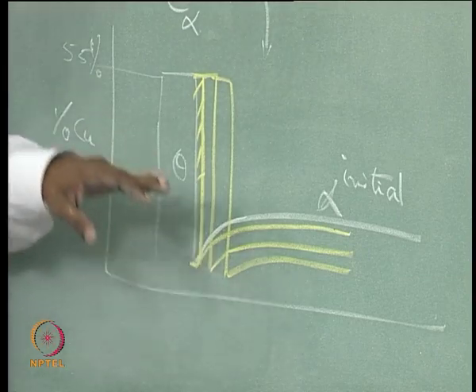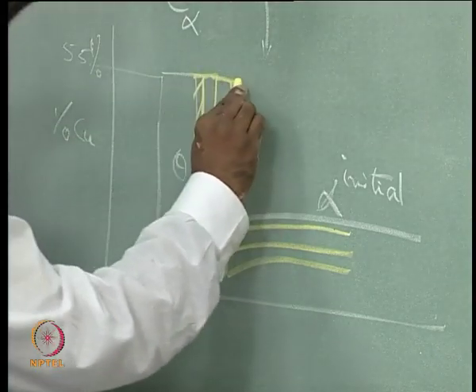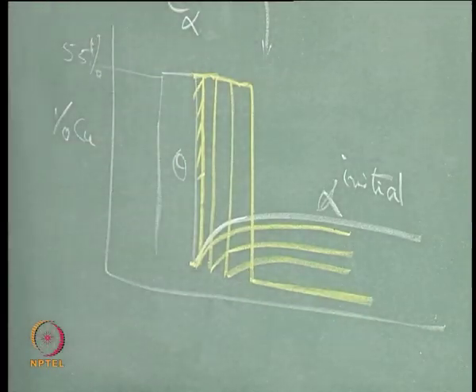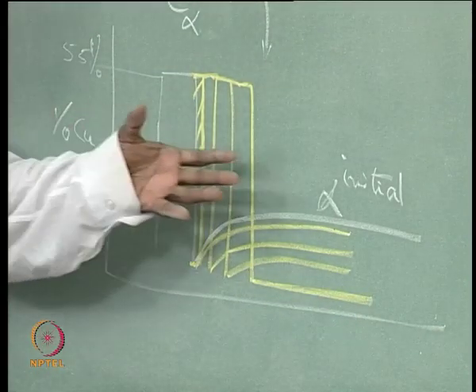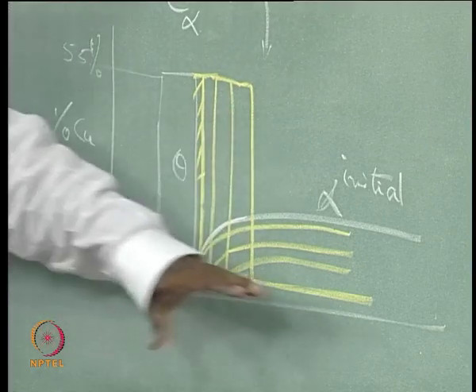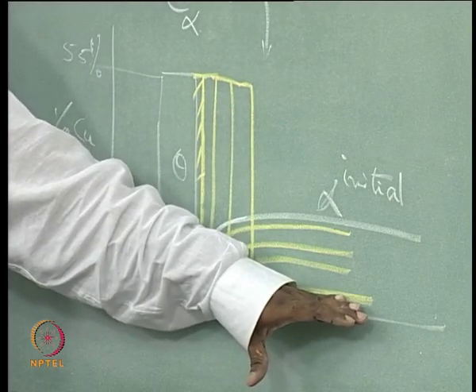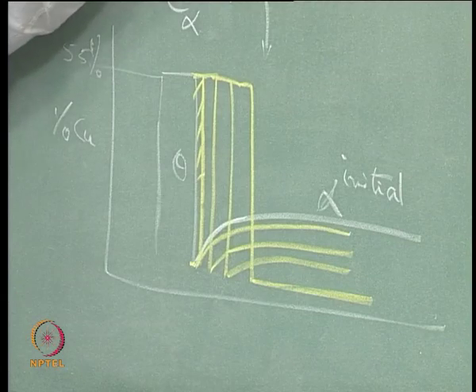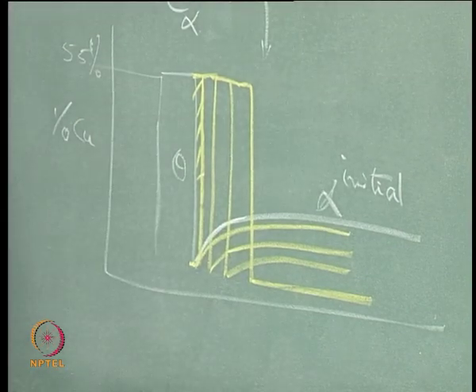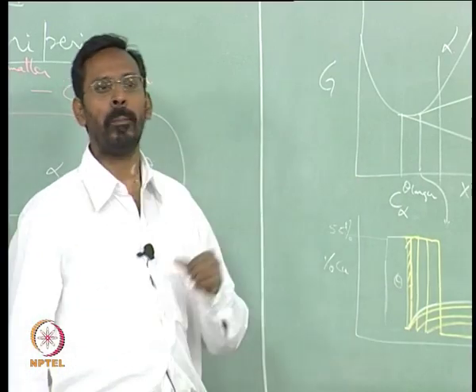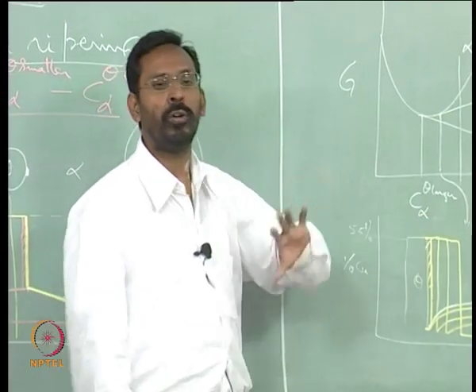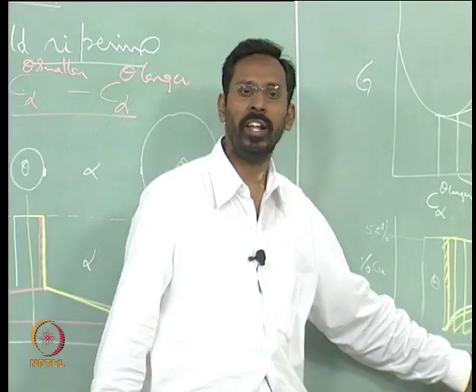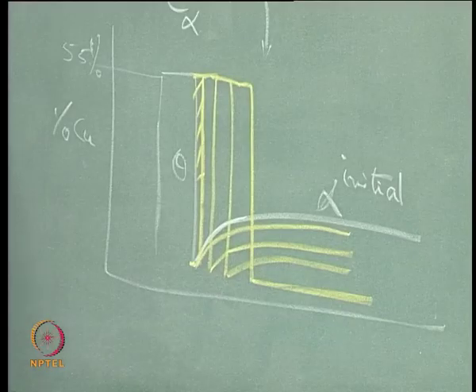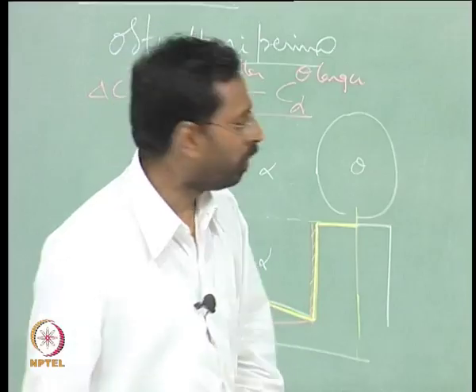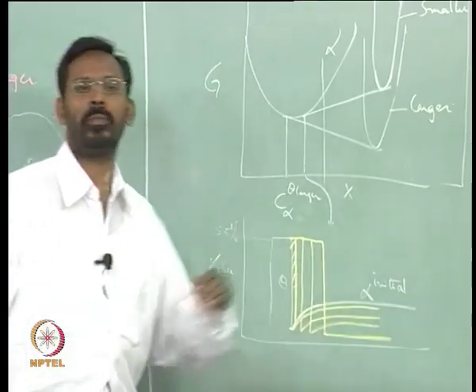So, as a result, after some time the theta would have grown to a certain extent, and then the alpha composition comes to that of the equilibrium composition. That means there is no more excess copper left in the alpha to be supplied to the theta. So, now the growth stops. Once this happens, the gradient is 0. Once the gradient is 0, there is no flux, and if there is no flux, there is no growth. So, this is how the actual precipitation takes place.